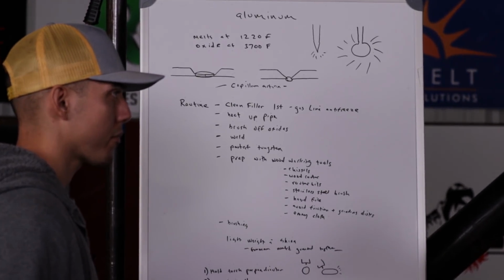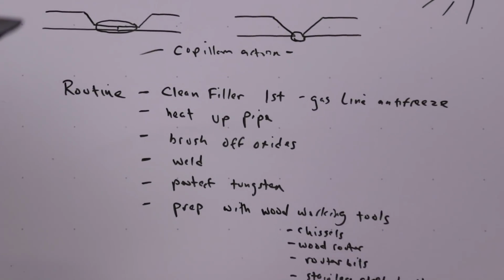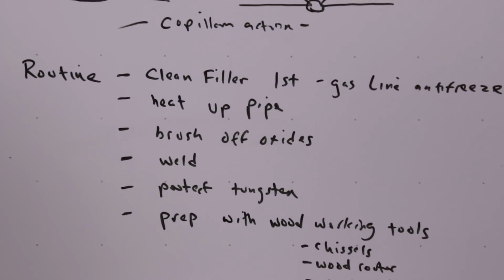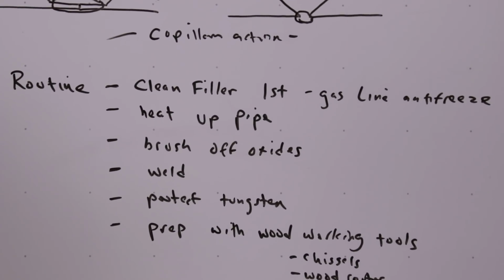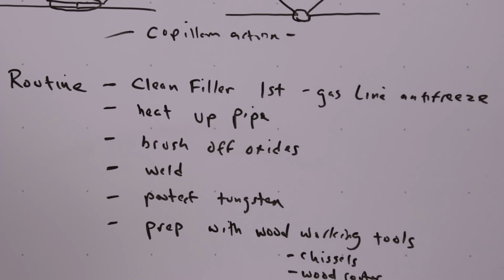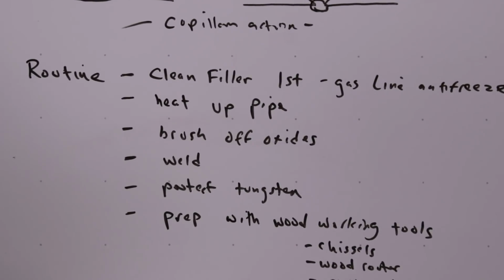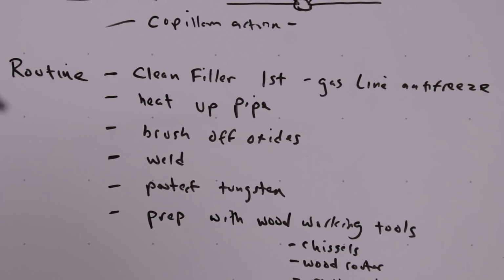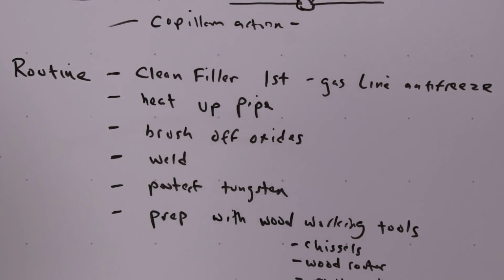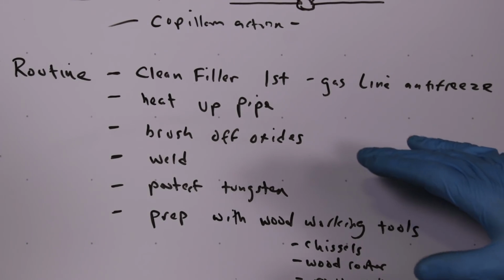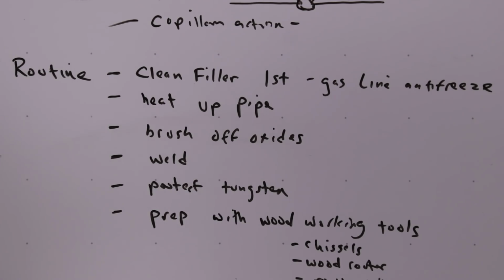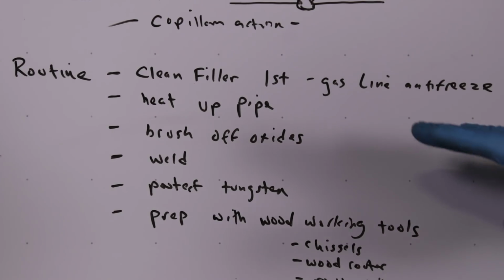Now, when I heat up the pipe, the problem with aluminum is that the hotter I get it, it starts rapidly forming oxides very, very fast. So when I heat it up to try and weld it, it's going to rapidly form oxides. And that's one of the biggest problems with aluminum, the rapid formation of oxides to protect the material. And immediately I'm going to brush the oxides off in the weld zone and the heat affected zone. I'm going to brush those oxides off in one direction, and I'm going to attempt the weld. But that's after it's been heated up.